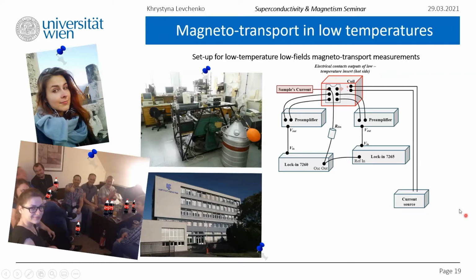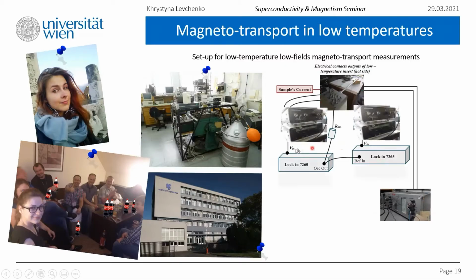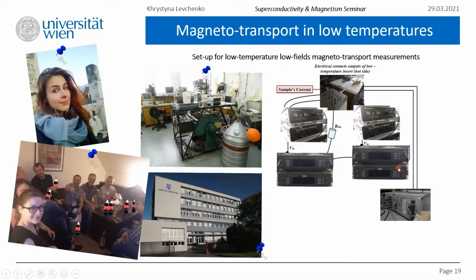Measurement setup consisted of the current source, which is voltage controlled, and 2 interconnected lock-in amplifiers that are further connected to the outputs on the sample low temperature insert through the voltage preamplifiers. On the low temperature insert itself, there is a sample mount table, which is not visible here, with a removable coil on top. Then there are 8 electrical wires hidden inside the stainless steel pipe, connecting the sample contacts on the mount table, which is a cold side, with externally hermetically sealed BNC connectors, the hot side of the insert.